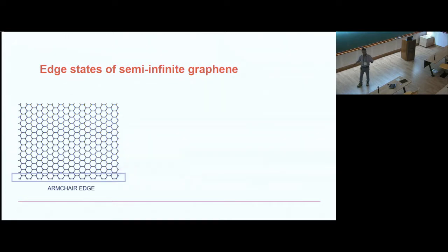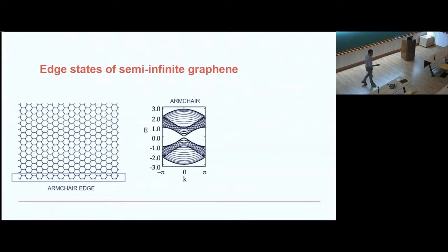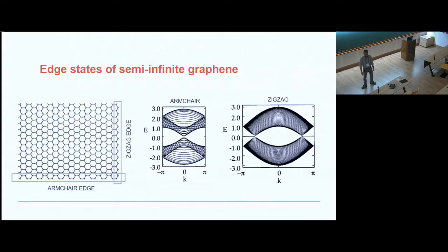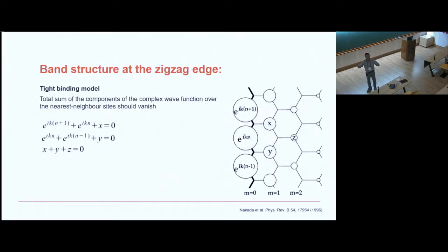Now, if you calculate the density of states and the band structure of the armchair edge, then in that case, it turns out to be a simple semiconductor. We have a beautiful gap opening up in the armchair. However, if you take the zigzag edge, then you start seeing a very different kind of band structure, where a new type of zero energy state appears. Again, as I said, there's nothing called topology here, because all you need to do is calculate. So a plain and simple tight binding model, you take the edge wave function and then assume that this is one particular value, the other value is orthogonal, so you have to have zero wave function, zero component here, and use that, and you will get the zero energy states.